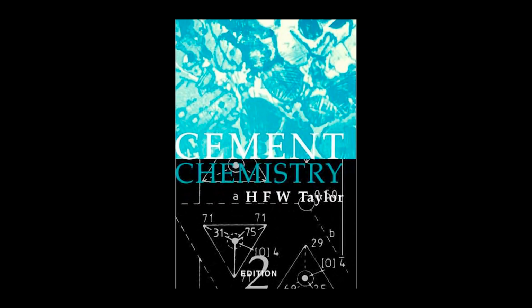Correct. The core of a ferrite crystal might be richer in iron, in Fe3+, while the outer regions are richer in Al3+ because they crystallized at slightly different temperatures as that liquid solidified. This is purely a function of the rapid non-equilibrium cooling.